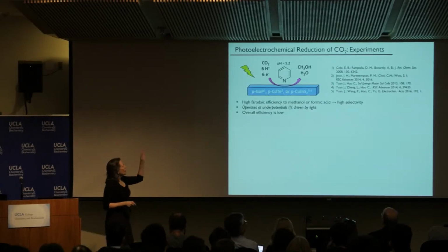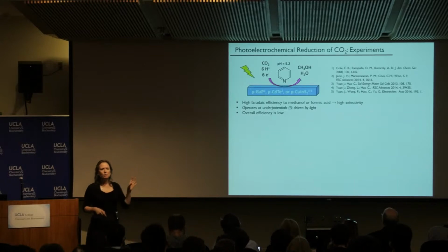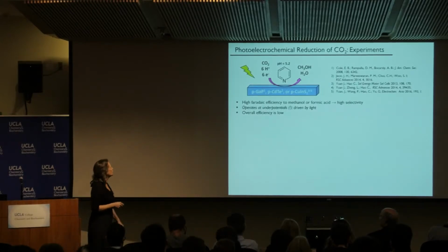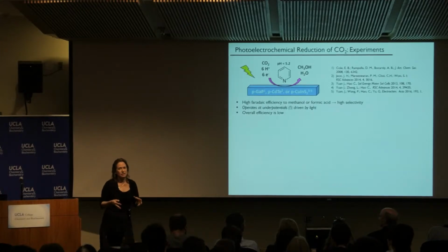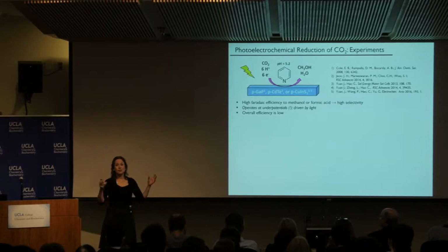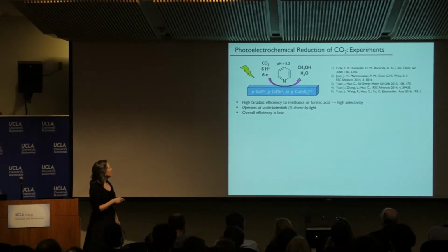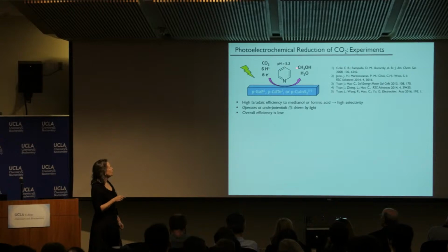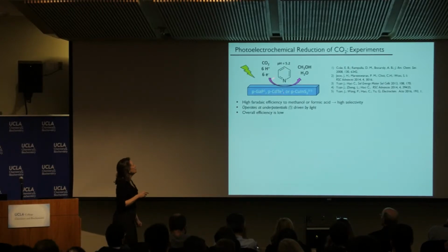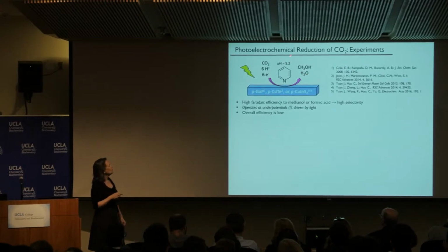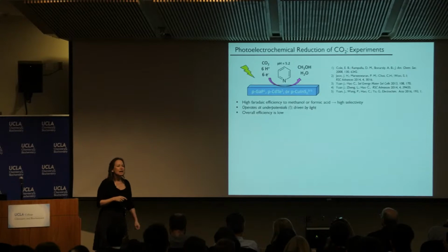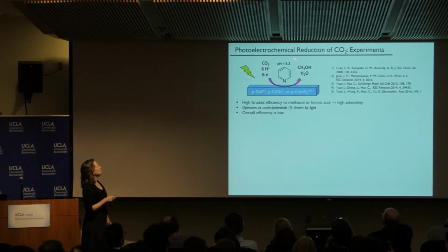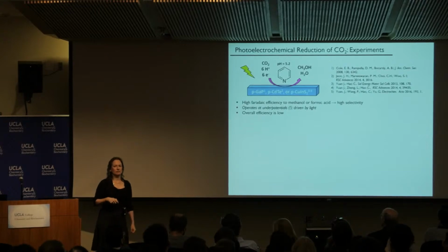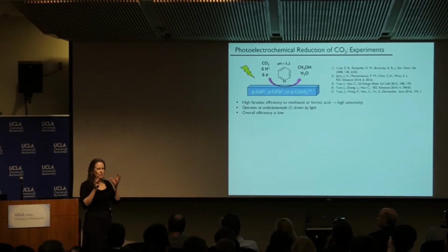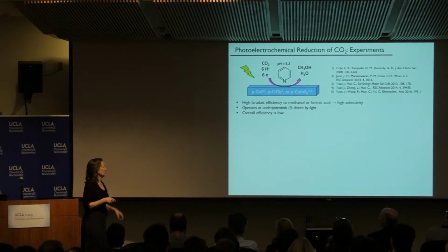Okay, so I'm going to summarize in one slide some experiments that are key experiments and conclusions of things we've learned from them. Turns out there are very few electrodes that do this kind of catalysis, and none of them do it very well, hence the need for R&D. And one very interesting set are these particular semiconductors that can take CO2 either to methanol or to formic acid, and they do it in slightly acidic water, so pH of 5.2, and it only works selectively in the presence of about 10 millimolar pyridine. So it's really interesting, right? It's just this interesting concoction, and the question is, we wanted to understand why that particular concoction.